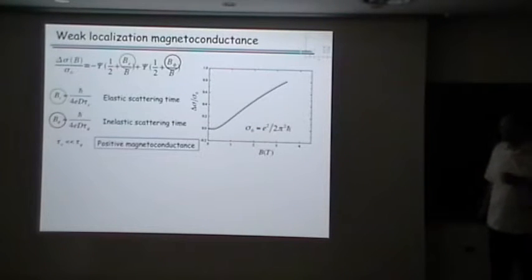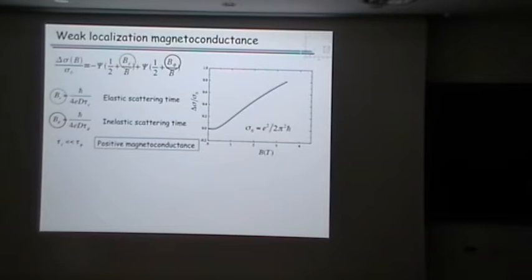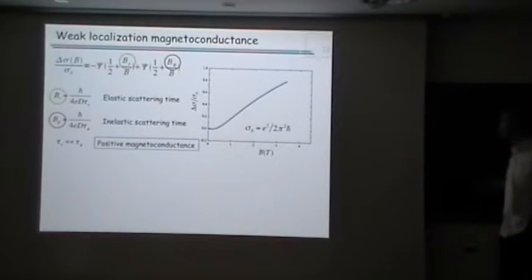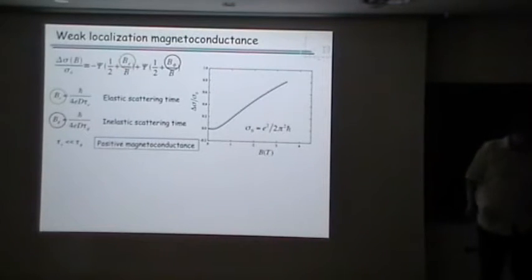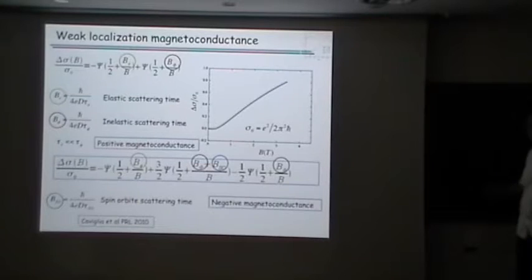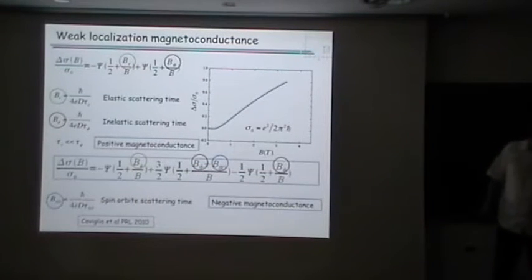This has already been observed by the Triscone group, and also the Dagan group and others. And of course, you think about localization corrections. The localization corrections are very simple. If you have only localization, then with the magnetic field you are increasing the conductance because you are cutting interferences. In this case, you have positive magnetoresistance. But if you put spin-orbit in the system, then things change, and you have those two terms in the magnetoconductance, and it makes a negative magnetoconductance. If you only use these two contributions, you're not able to fit the data correctly.